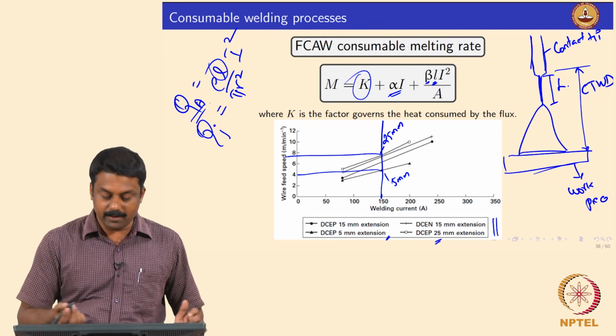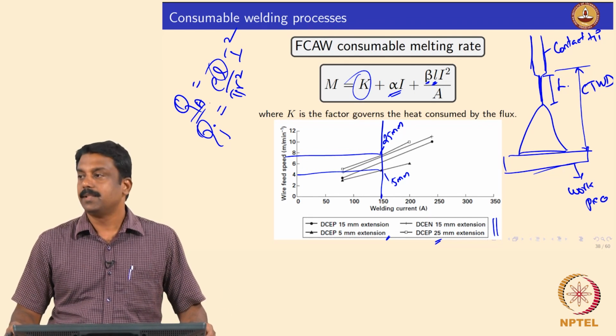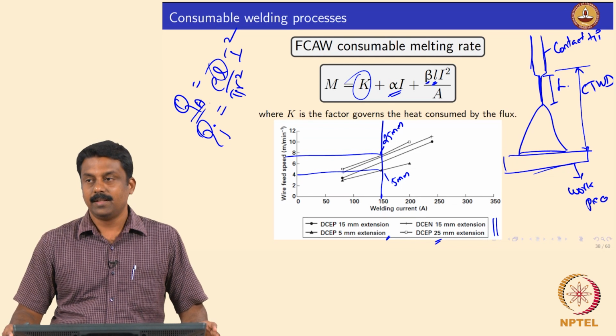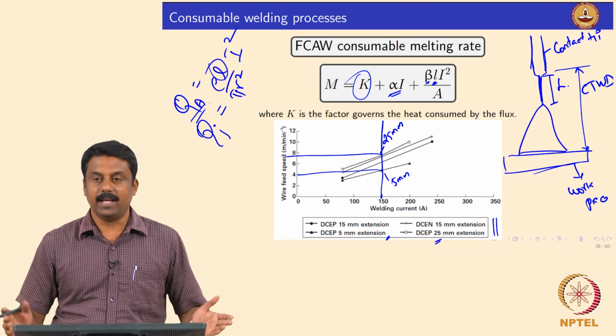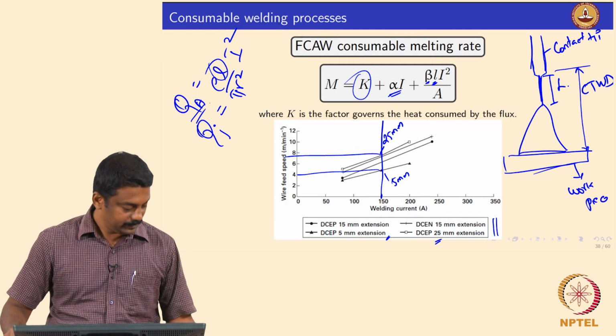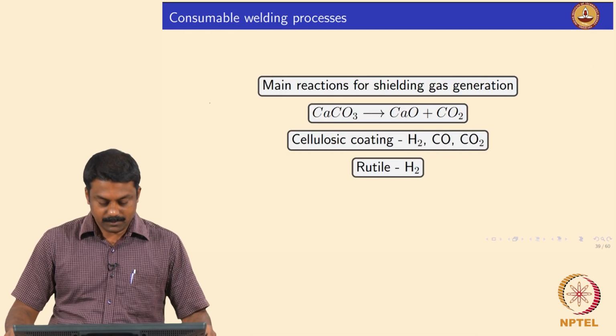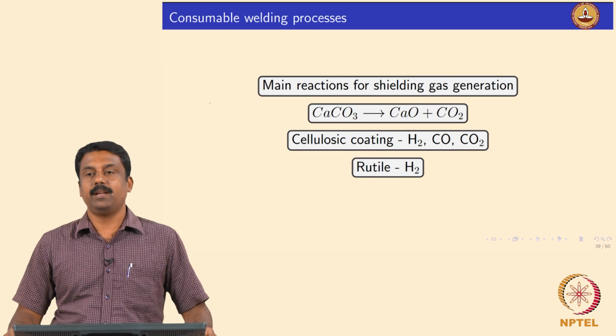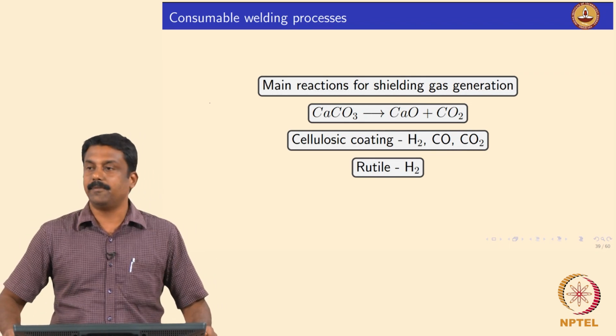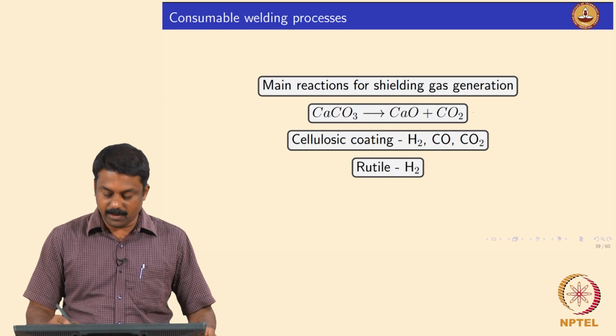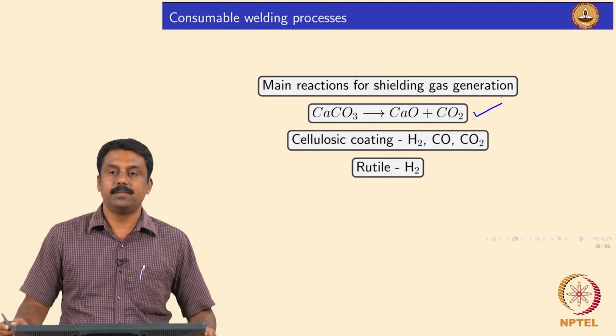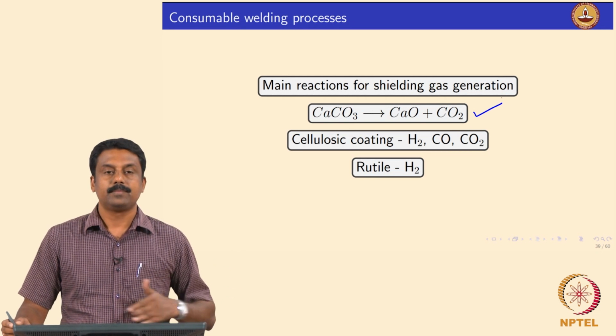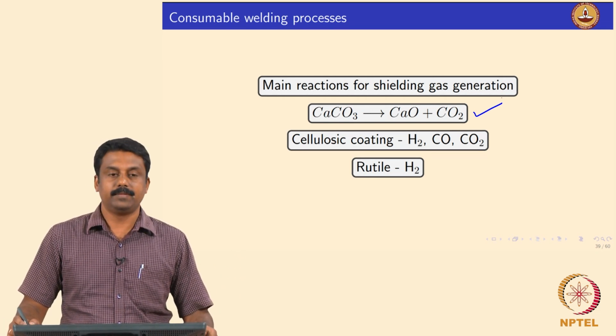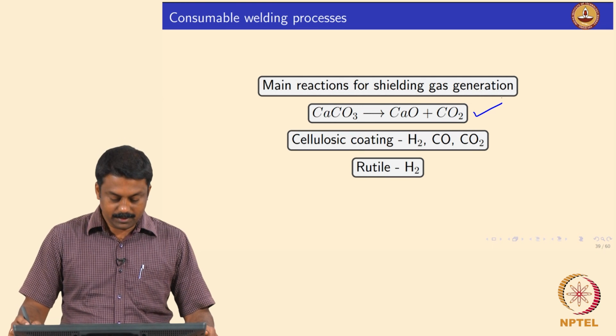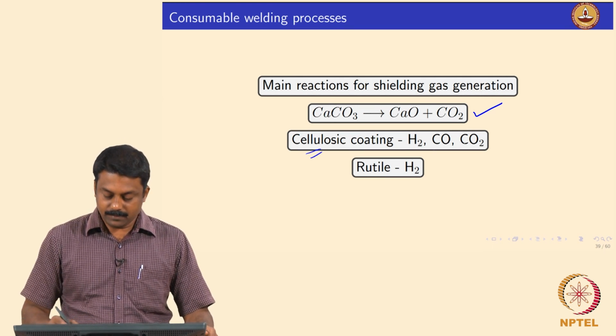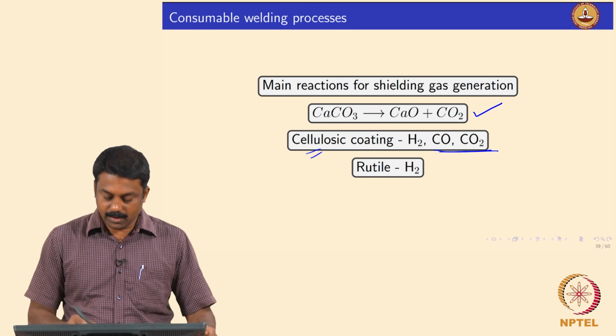So, the K factor takes care of the heat consumed by the flux by decomposition to generate hydrogen, the gases, carbon dioxide, the other shielding gases. Good. So, the main reactions for shielding gas generation in these flux coated electrodes or FCAW electrodes is calcium carbonate burning into calcium oxide and CO2, and calcium oxide forms a slag and CO2 is a shielding gas. Okay. So, in cellulosic material the fluxes generate carbon monoxide and carbon dioxide and also the hydrogen.